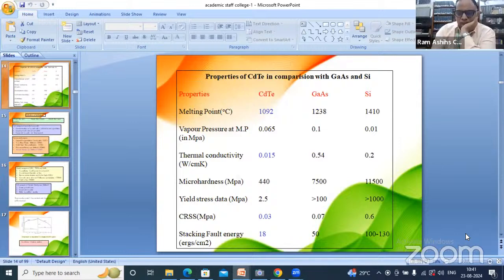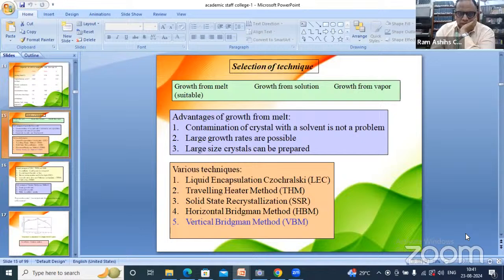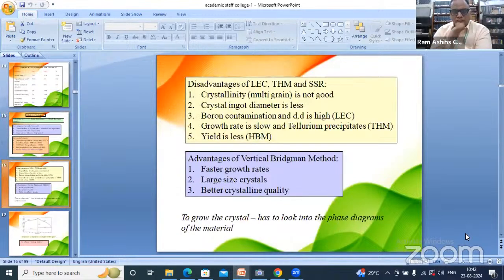These are some parameters of the cadmium telluride, gallium arsenide, and silicon crystal. Now, these are the advantages of growth from melt. Contamination of the crystal with solvent is not a problem, and large growth rates are also possible. Large size crystals can be prepared with this technique, and other techniques are the liquid encapsulated Czochralski method, traveling heater method, and solid state recrystallization method. In the Bridgman method, two methods are there: horizontal Bridgman and vertical Bridgman. Here for large area grain or single crystal purpose, we are using the vertical Bridgman method as a unidirectional freezing method.